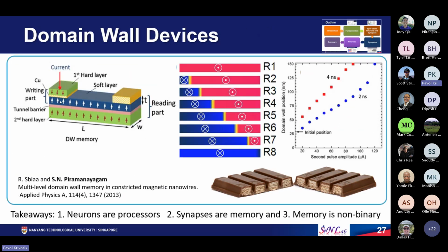the current will flow through the blue layer on the top, and it will return through this lead. And we can create a spin transfer torque in this region, which can change the magnetization direction of this region from pointing up to pointing down, which is shown by the blue color. So in this picture, the red means magnetization is pointing up, blue means magnetization is pointing down. And when you send one pulse of sufficient magnitude, you can change the magnetization of this region.